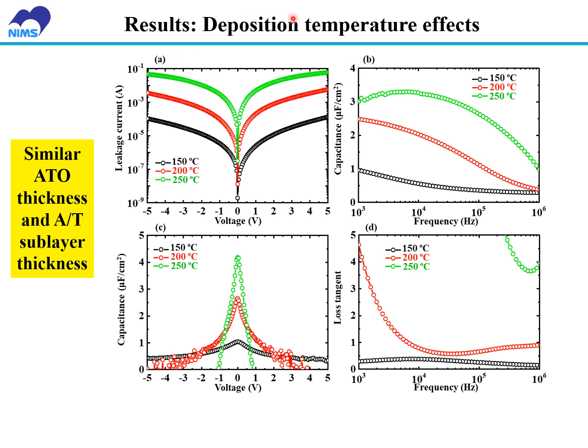Next, I will show the deposition temperature effect on the electrical properties of the capacitors. The deposition temperature for the ATO nanolaminate was changed from 150 degrees C to 250 degrees C with a similar ATO thickness and a similar sublayer thickness. With the increase of deposition temperature, the leakage current density also increased greatly.